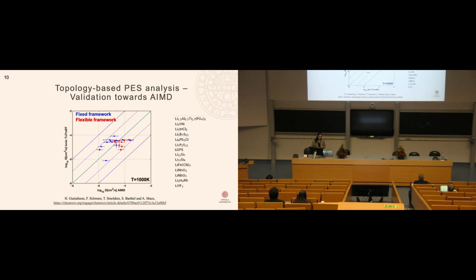So the next step is to validate this. Now that we're able to compute these diffusion coefficients at a manageable cost at a DFT level of theory, we need to validate them against DFT-based molecular dynamics. The biggest challenge of this validation is the high computational cost of performing the DFT-based molecular dynamics, and its limitation to only being able to probe the diffusion for the very fastest ion diffusers. So we're in a very limited range of diffusion coefficients that we can validate against.